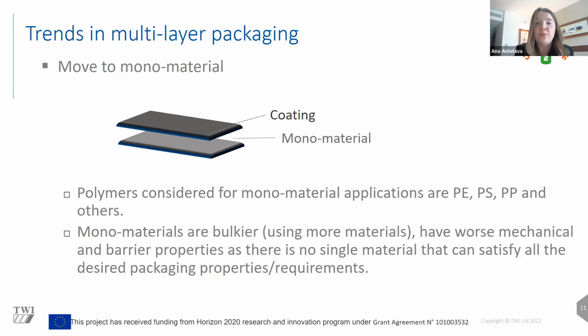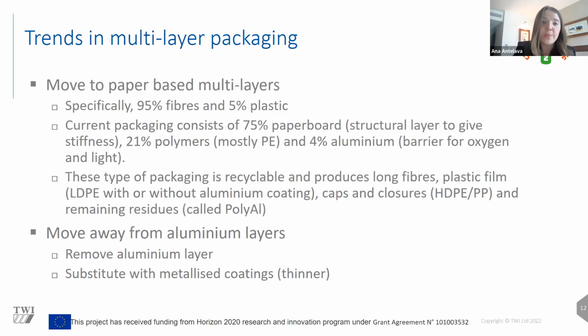Another issue that might arise is that when you have the monomaterial, you might have some printing on top, labeling, and you might also utilize coating that will protect it. So in a sense, that also presents a challenge of separation of different materials. Another trend that we saw was the move to paper-based multi-layers. Specifically, the target is to move to 95% fibers and 5% plastic. From the consultations, we found out that currently paper-based cardboard packaging consists of about 75% paperboard, which gives packaging its structural layer, 21% polymers, and 4% aluminum. So the industry is trying to reduce the use of polymers, remove aluminum and increase the paper-based layer.